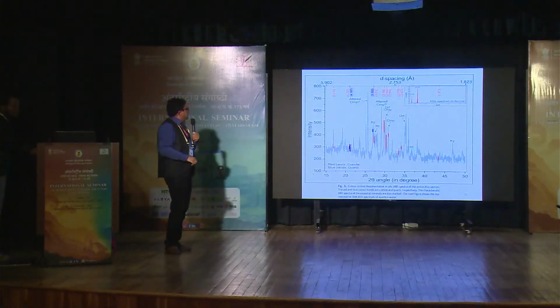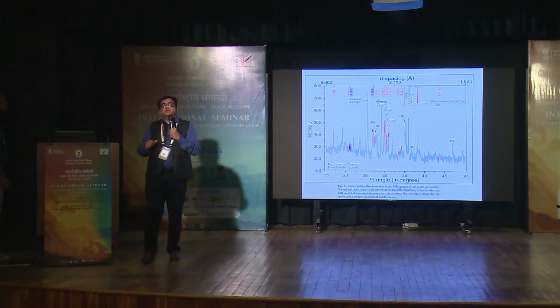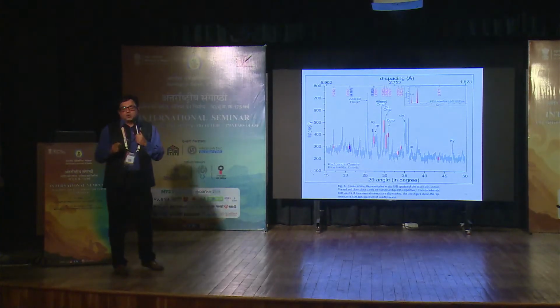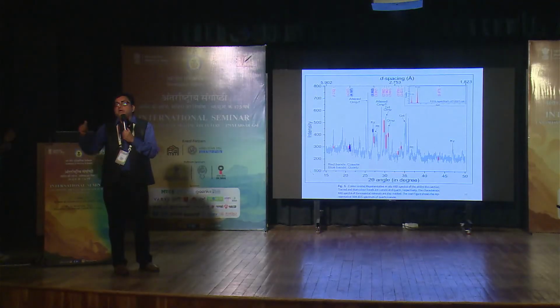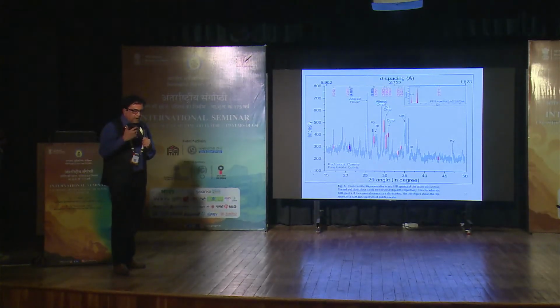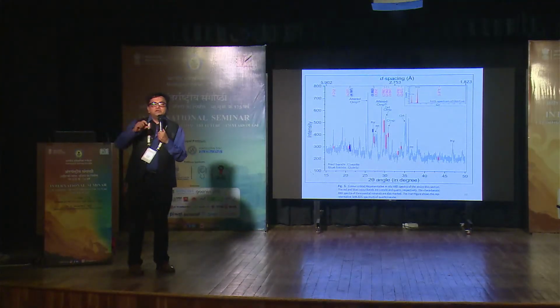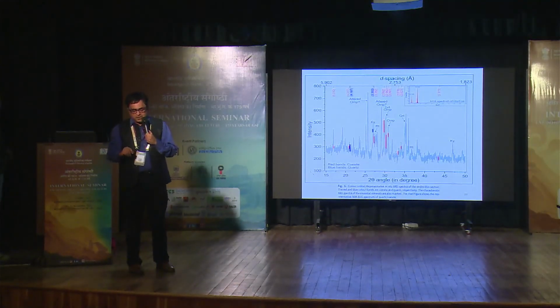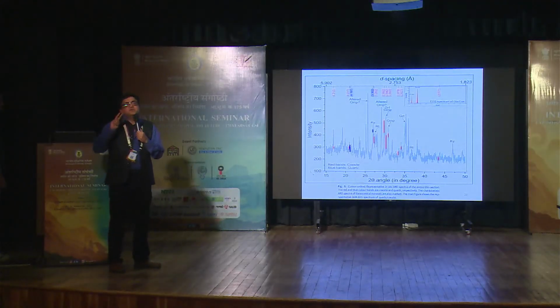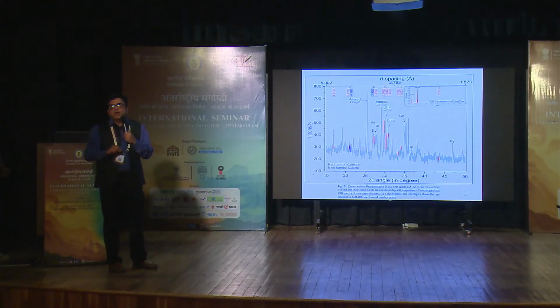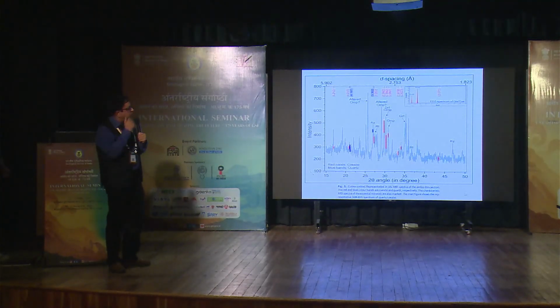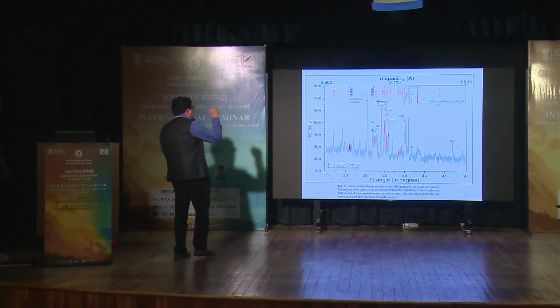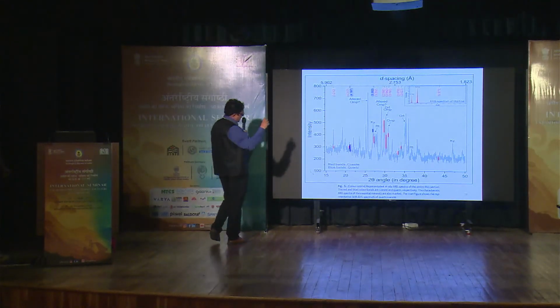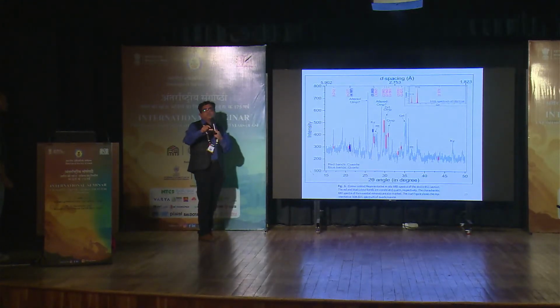Next one. Then it was at thin section scale. Now how to confirm? Because for powder XRD, you need to separate and make a powder. So then we were looking for an XRD in India where it can analyze the different phases at thin section scale. Then we realized there are two places in India where such a facility exists. One is at IUAC New Delhi, the other is IISc. And the IISc facility was down during COVID time. Then Amitava went to Delhi with some difficulty, and we could work on that IUAC XRD, where you can use your thin section and bombard it with X-rays